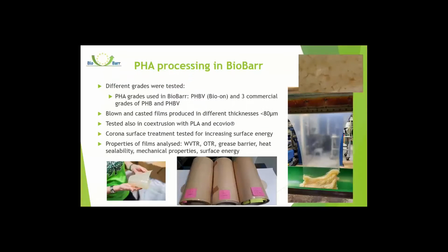Different grades that we tested. So I already mentioned the PHBV from Bio-on that we had in the beginning of the project, and we did several tests and trials with that material very successfully. And after that, we worked with 3 commercially available grades of PHB and PHBV. And the different materials were tested in blown and casting processes. So we produced films with these 2 processes in different thicknesses, less than 80 microns.